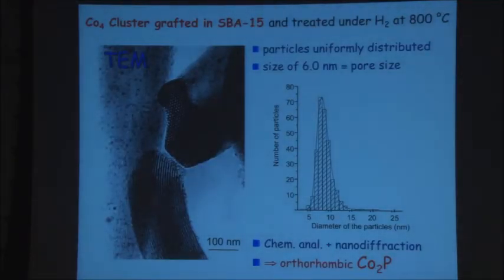You look at TEM, and indeed you see in the channels of your matrix small metal particles. That was done with SBA-15. So the particles are uniformly distributed. This is the histogram, and you see that the size is about 6 nanometers, and that corresponds to the diameters of the pores, which suggests that indeed we have a confinement effect. The particles do not grow too big because they are confined by the diameter of the mesoporous materials.